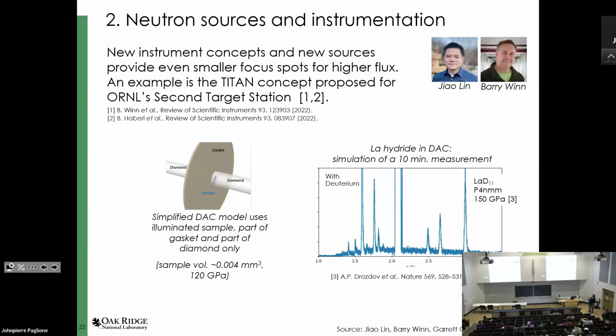And here's a simulation of a diamond anvil cell and the sample we would have in our typical neutron diamond cells at 150 GPa if this sample was an actual lanthanum hydride. So this is not something we can measure at the moment yet. We don't have that instrument. But if we can push the development, eventually we can really do 10-minute exposures and get a reasonable diffraction pattern at these pressures that are critical to the metal hydride community.